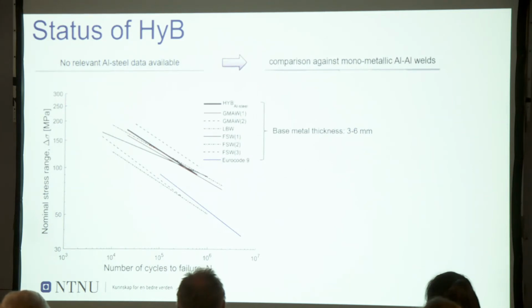There are not relevant aluminum steel data available in the literature, so we have compared our aluminum steel data with the data from aluminum welds present in the literature. And what is evident is that HyB is here. So for the base material, we are over what is happening for aluminum steel, which is quite good and much higher than Eurocode 9.